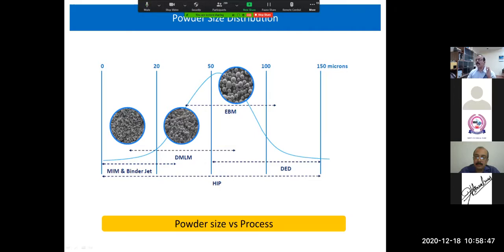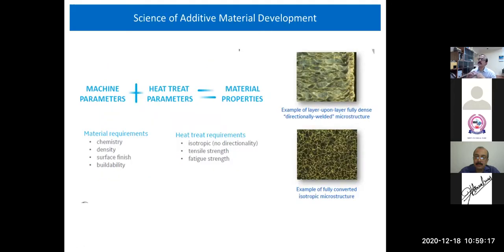And definitely for all these parts, it has to be hipped, that is the hot isostatic pressing. You put the part into a furnace, we call it a hipping furnace, and you apply pressure and temperature. All the pores will close down, and the grains deform so that it closes down, and you get a very high strength.